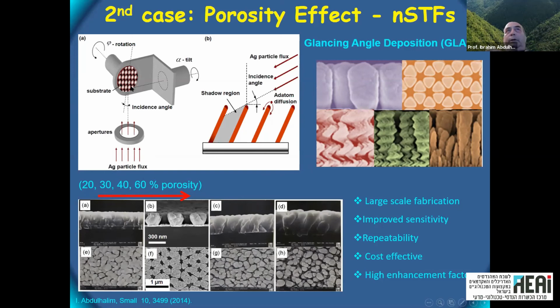When you deposit at large angle, you start to deposit the material, and then because of shadowing effect, it starts to grow in columns. So it means you have like a porous material. These columns are nano columns, actually. They have a width of like 20 nanometers. So actually, the scattering is quite small. They are close enough, like 10, 20 nanometer voids between them. They are random. It's still conducting, depending on the porosity, of course.